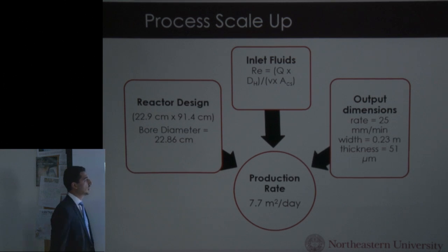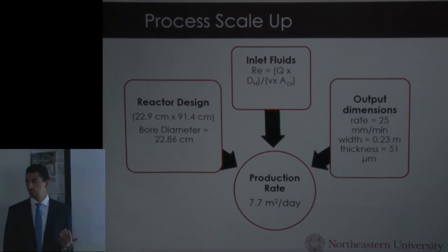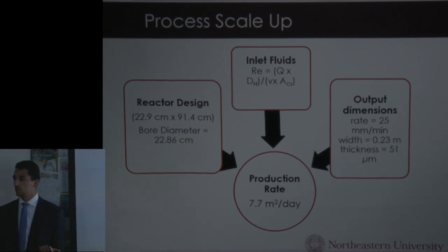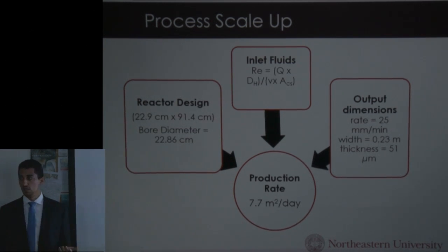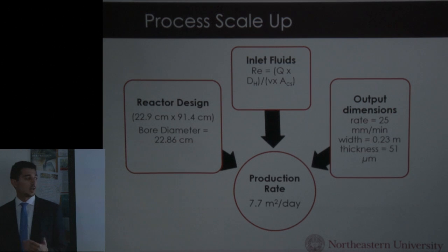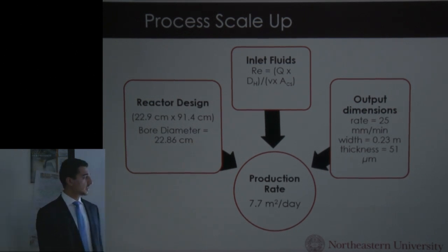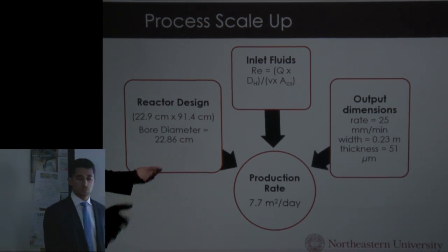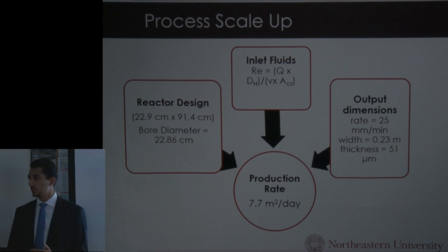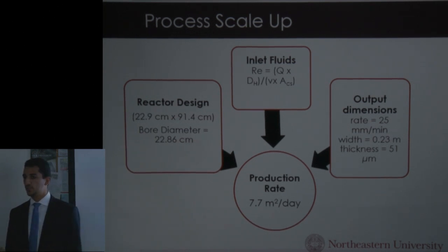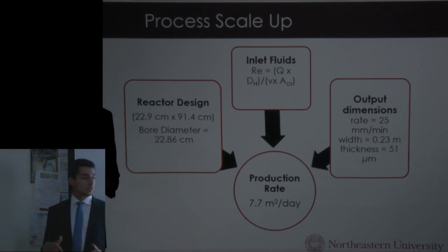Additionally, the second criteria was the inlet fluids and raw materials. For the gases used, we had to scale them up using Reynolds number, such as for the helium and hydrogen. For the final criteria, which is the output dimensions, which is the dimensions of the copper substrate leaving the reactor, it will be leaving the system at a rate of 25 millimeters per minute, and the thickness is estimated to be 51 micrometers, while the width is almost 9 inches.